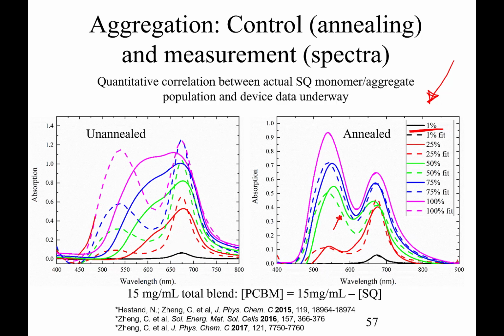Here's 100% aggregate, and here this double hump, and what do the data actually show us? Well, we've got these strange features here. So in fact, what's happening there is we've got in the amorphous blend, we have very closely packed squaraine materials, but rather than have molecules that are aligned in a very definite crystal geometry, what we have is a lot of molecules that are all randomly oriented, and we have different dipole interactions between these unoriented molecules, and that's what gives rise to this. This is a dipole-dipole interaction that we start to see manifested at around 600 nanometers.